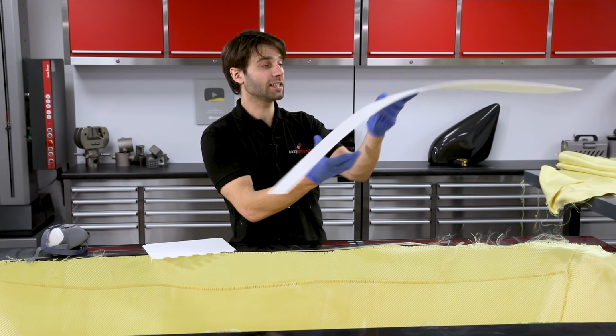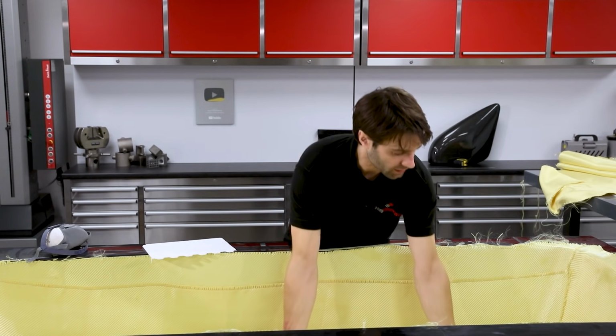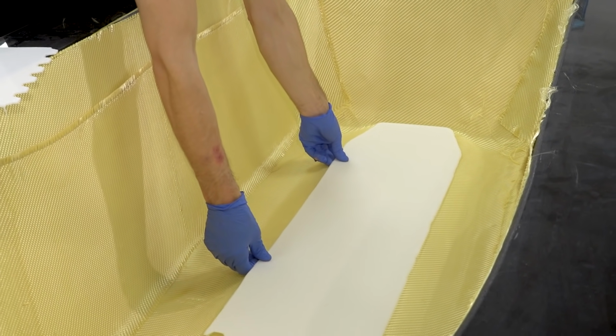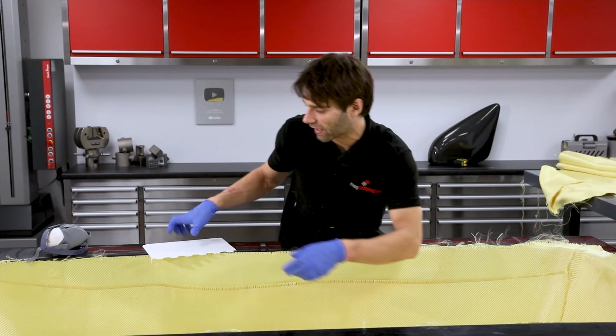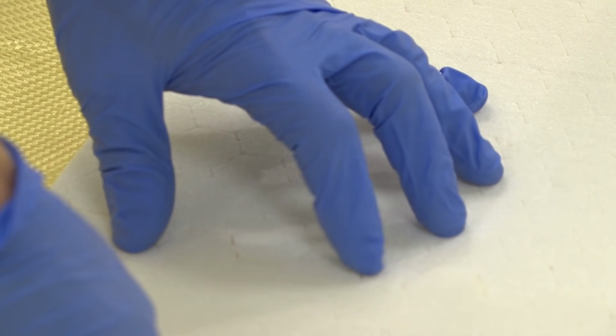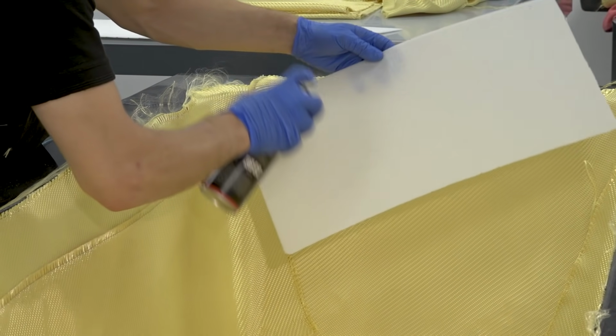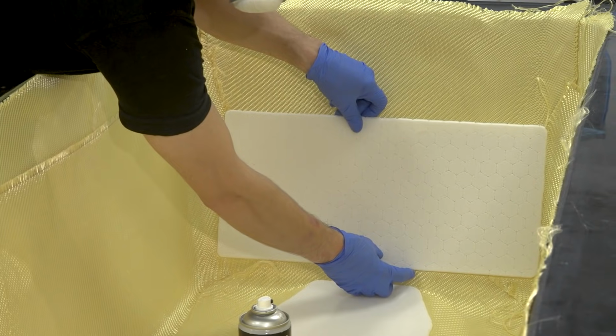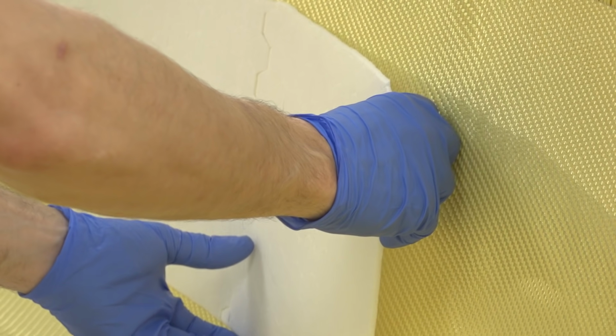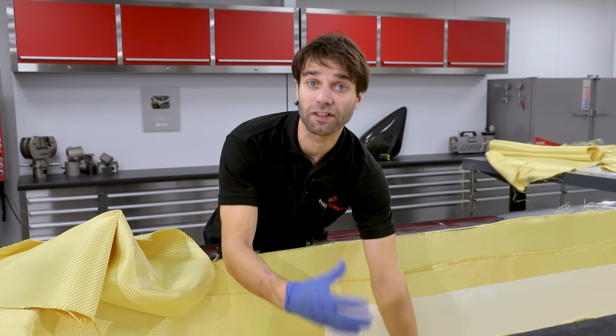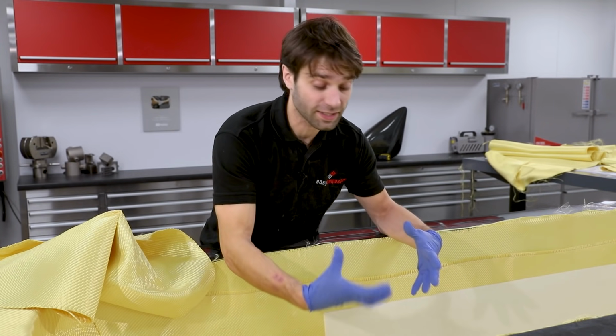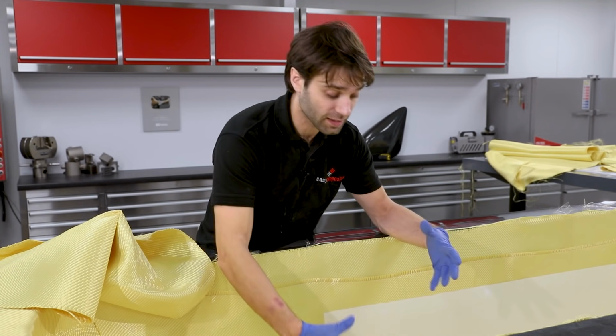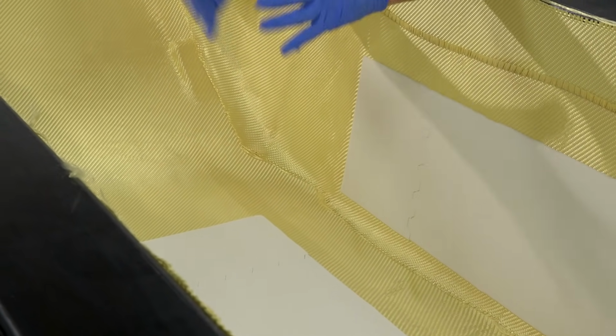The next layer in this case is the core material. So that's going to be sandwiched in between the Kevlar and give us that additional stiffness in the flat areas. So the core materials are positioned in the areas where we want the most stiffness, but not necessarily where they'll be subjected to a lot of impact. So the main run of the base and the sides and the rear.